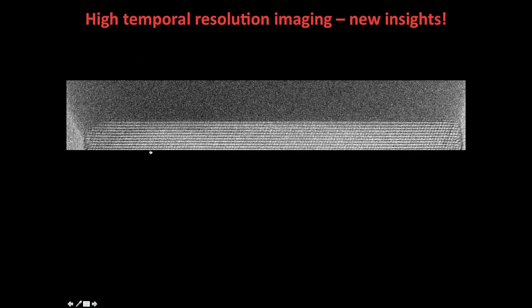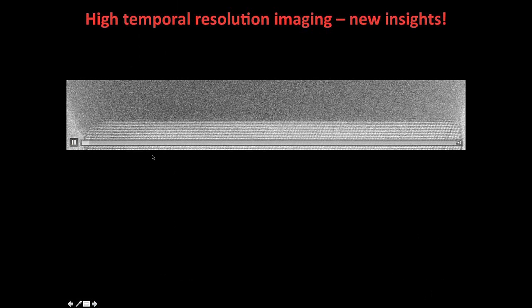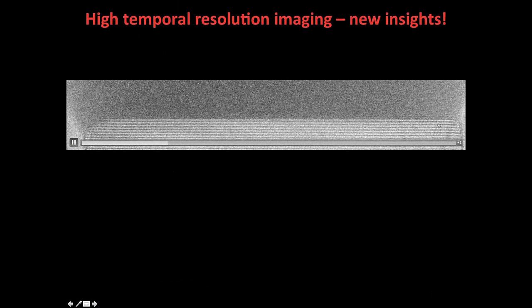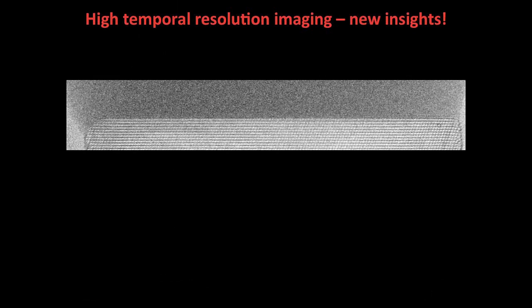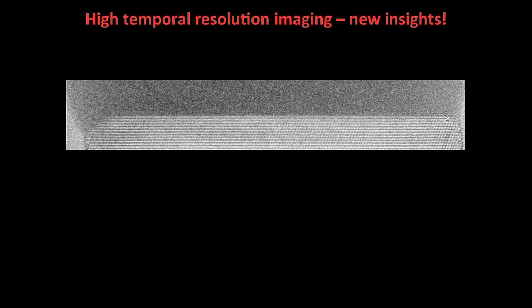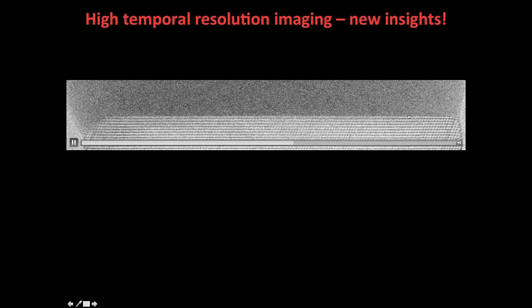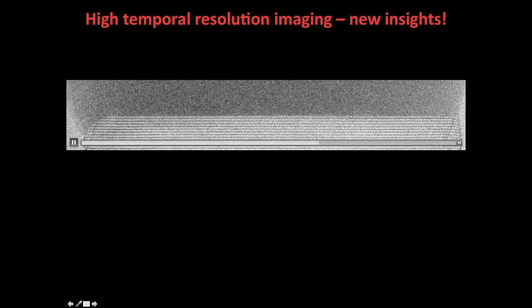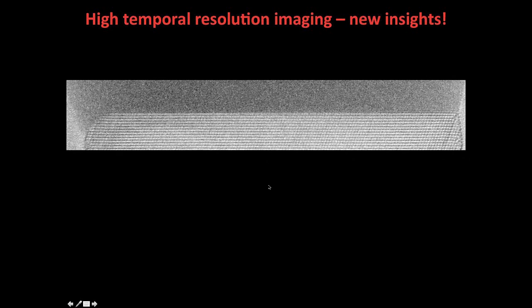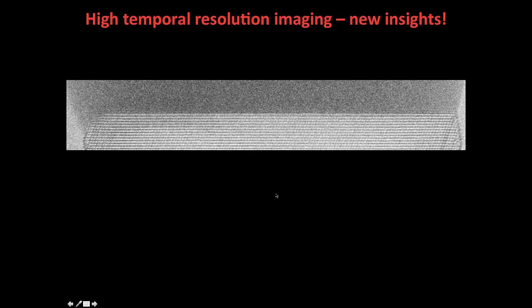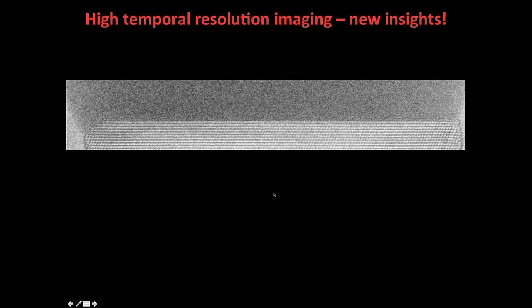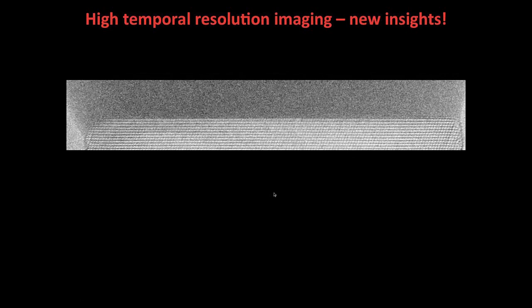So if we go a little bit further, these are some images taken at this interface at 400 frames per second. They're a little bit noisier because you're at a higher level of magnification. Your dose has gone down a little bit, but you still see, I think, very good quality images of the individual atomic layers as they slide on in here and create the new piece of silicon through the growth process. And a quick comment here: you can take videos, but you can also use these to do lots of analysis. That was an example of the types of things you can get with this.